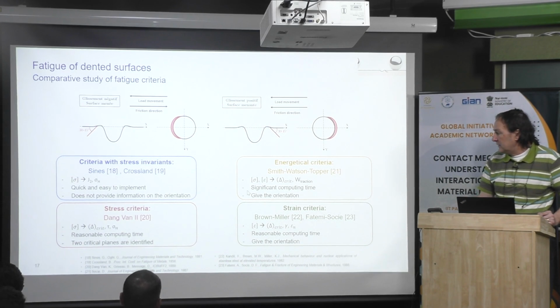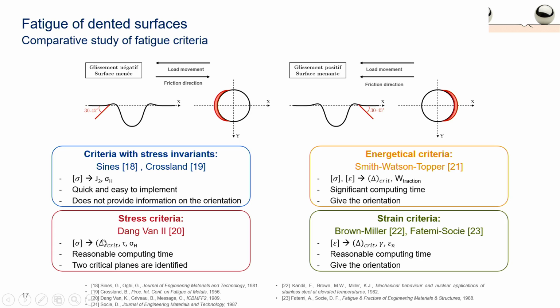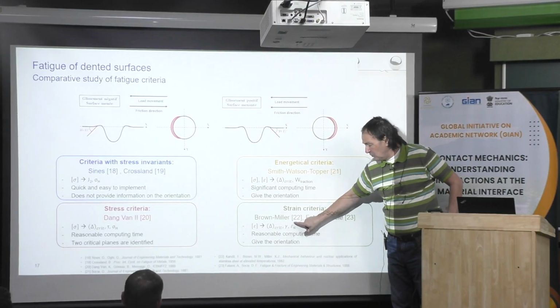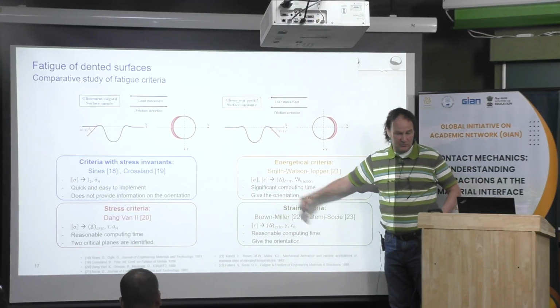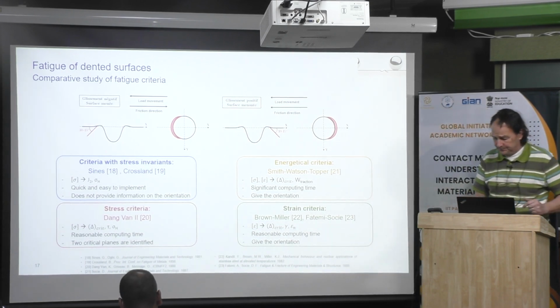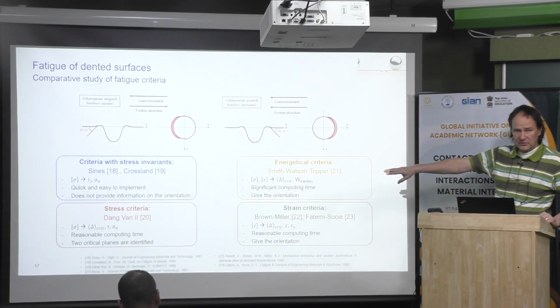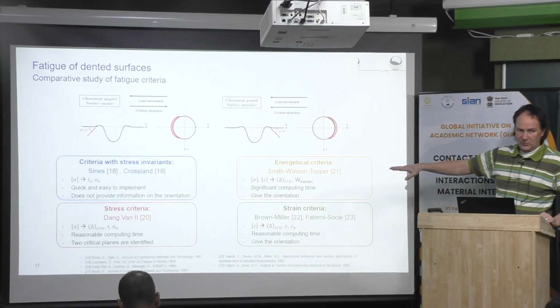And for this model here, you have the critical plane where the crack can propagate. You have the shear stress, or the Tresca shear stress, equivalent to Tresca, and again the mean stress. And instead of working with the stress, you can work with the strain. Then you have the shear strain and the normal strain. It's equivalent, in fact. You just have to deal with other parameters. And the Dang Van, I don't know if you know the Dang Van criterion. It's very well known and used in France with a lot of companies.